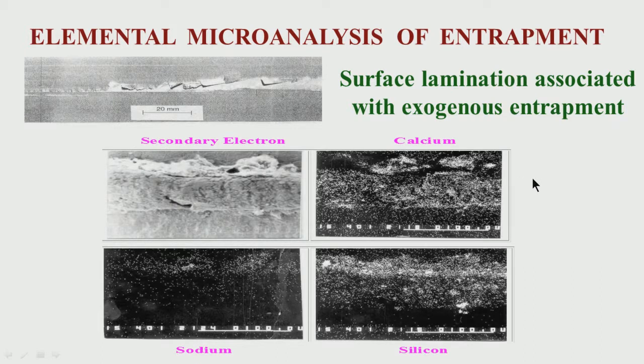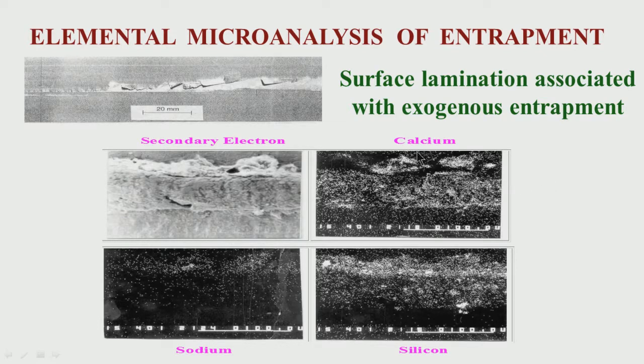In a scanning electron microscope with a WDX or EDX attachment, electrons falling on the surface generate X-rays. From the wavelength of these X-rays, we can know what elements are present in the exogenous entrapments. The defect under an optical microscope looks a certain way, and under SEM with secondary electrons it looks different. From elemental X-ray analysis, we can identify elements such as calcium, silicon, or sodium, which give definite clues as to the genesis of the entrapments.